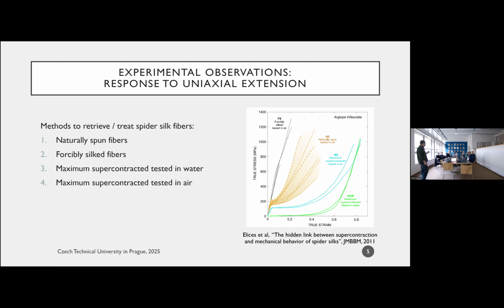So the way you obtain or retrieve spider silk fibers, there are a few ways of doing this. One of the ways that you can get this fiber from the spider is you can put a spider in a box and then just let it weave away, right? So you let it do its thing. It weaves the network, it weaves its spider web, and then you take the silk fiber and you stretch it. This is typically what we call naturally spun fibers, right? Because the spider wove them naturally. And naturally spun fibers behave in this way, right? So it's kind of this region here. There's variability because this is a biological material, so I guess that's a given, but you can see that this is the response, right? It starts out like this, and then it curves into this curve that you get. And if you're familiar, this is a very, very typical curve for glassy polymers, right? So glassy polymers behave like this.